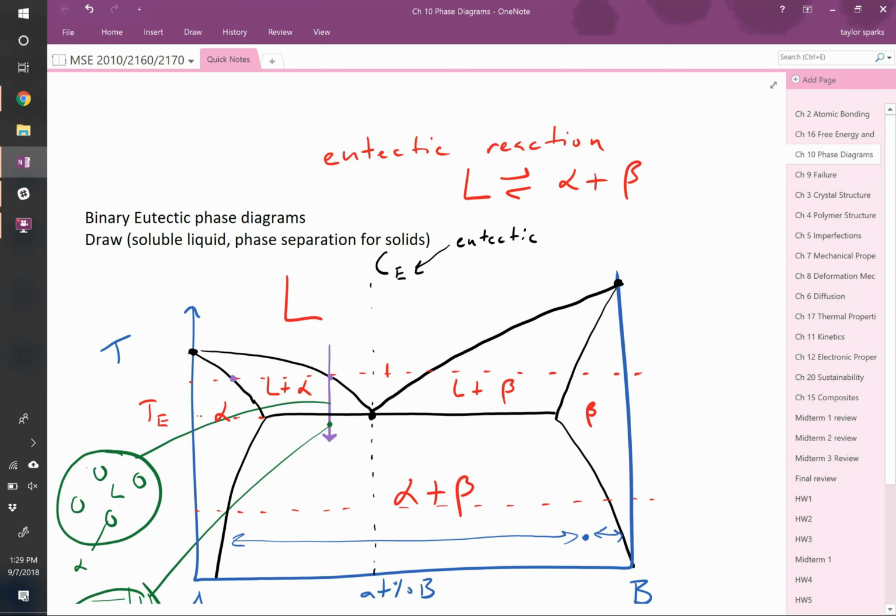Which means if I move up in temperature, let's say with my 1 degree of freedom, what if I move it all the way up to right here? Well, now this section of line is much, much larger still, which would mean I've got almost pure beta because it's almost touching this line. So the ratio, the amounts of those 2 phases has changed. If I want to maintain equilibrium with the same amount, it's going to tell me that I have to scooch over a hair and be right there. That make sense? We're going to do the lever rule and actually calculate this in a second. But does that kind of make sense? Why there's 1 degree of freedom there?